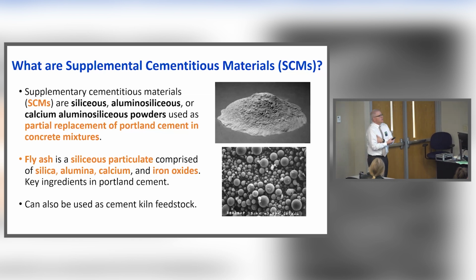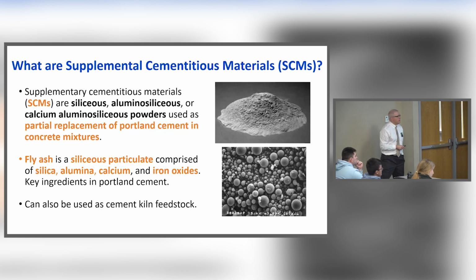So we could potentially avoid some of that by replacing the cement with so-called supplemental cementitious materials like the ashes. So the SCMs are silicaceous, aluminosilicaceous, or calcium aluminosilicaceous. We got silica, aluminum, and calcium, powdery-like materials that we can use as a partial replacement for Portland cement in our concrete, all right? And fly ash is this silicaceous particulate.